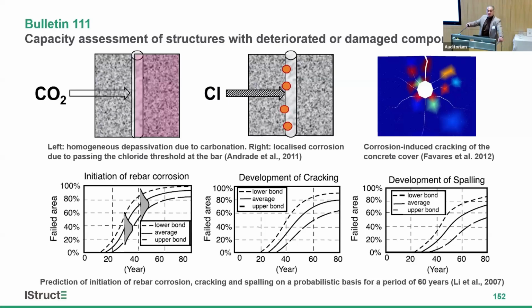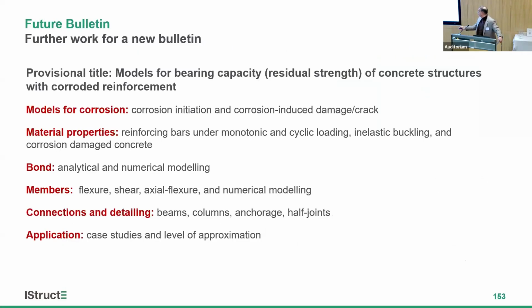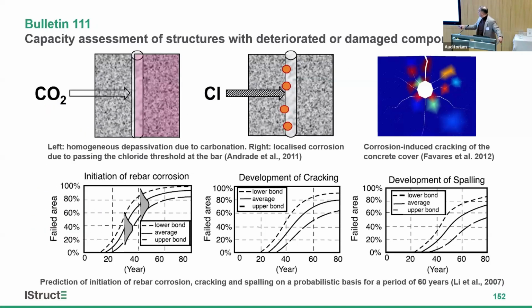That's not where the damage starts. When corrosion starts, it starts propagating if we do nothing, and we cannot normally see it unless we do NDT, non-destructive testing. Then when corrosion develops, it starts having some cracks, and eventually the concrete falls off. But between the corrosion initiation and the spalling, we have lost some reinforcement. We don't know the residual capacity, so we need ongoing measurement through inspection to be able to understand our structure. Spalling is essentially too late by the time we get to that stage.